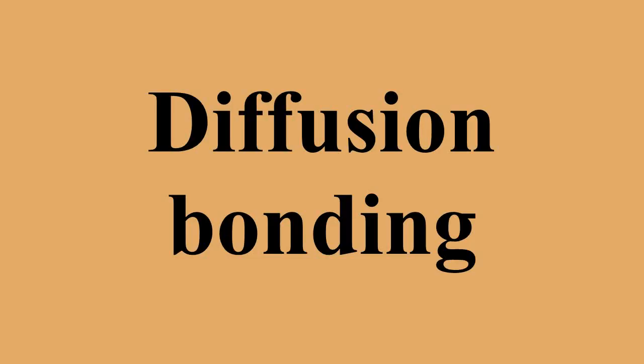Characteristics. Diffusion bonding involves no liquid fusion, and often no filler metal. No weight is added to the total, and the joint tends to exhibit both the strength and temperature resistance of the base metal. The materials endure no, or very little, plastic deformation. Very little residual stress is introduced, and there is no contamination from the bonding process. It may be performed on a joint surface of theoretically any size with no increase in processing time. Practically speaking, the surface tends to be limited by the pressure required and physical limitations.